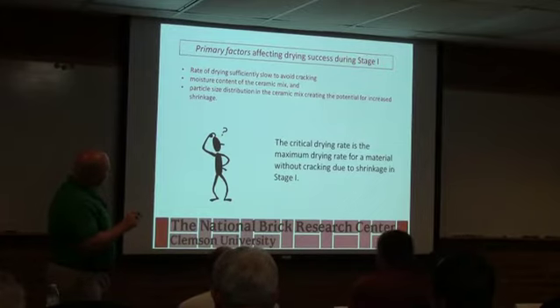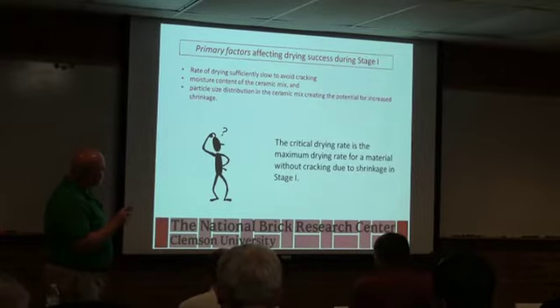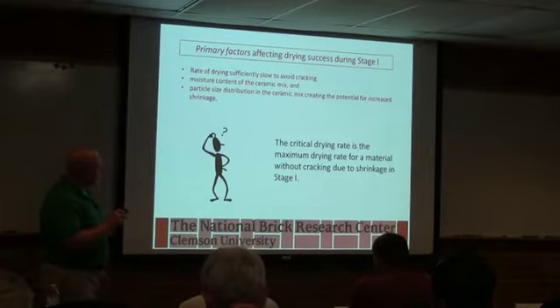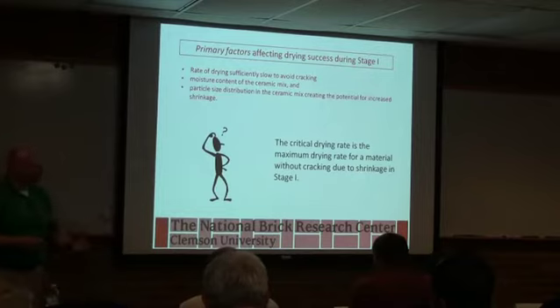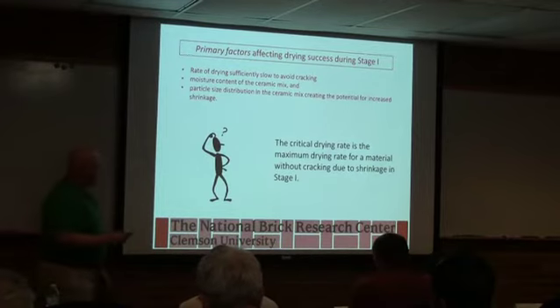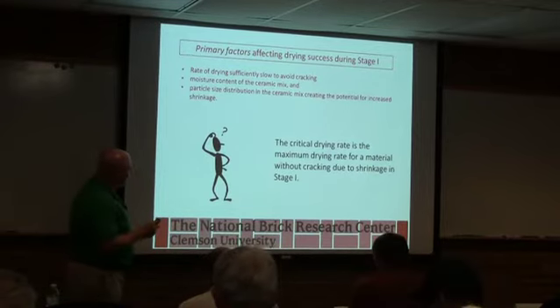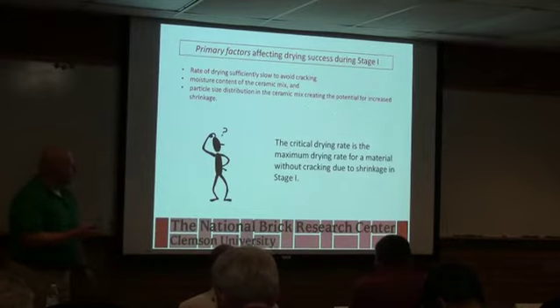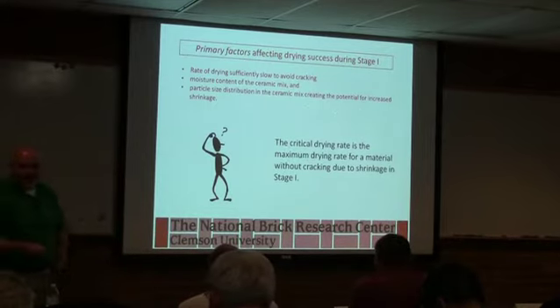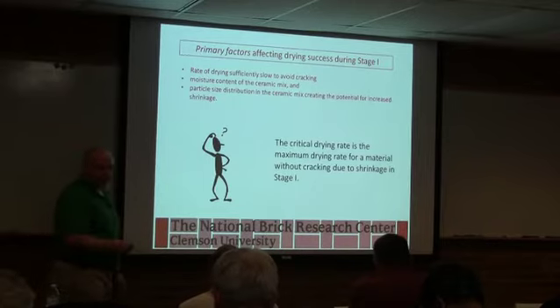So the particle size distribution is very important for controlling shrinkage. Typically we're interested in the coarse end of that size distribution to control that shrinkage. Very fine mixes tend to have a lot of shrinkage, a lot of drying difficulty. Coarse materials, there's some shales in North Carolina that make a pretty brick, but you can basically throw them completely wet in a dryer and it doesn't seem to affect them, because they're sufficiently porous that the water can get out.